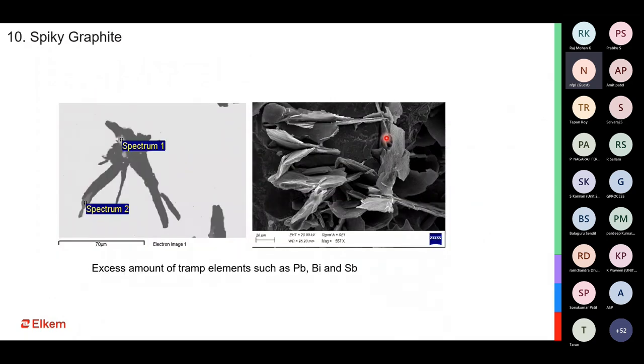Spiky graphite. Again, spiky graphite is something which can happen in both gray and ductile iron. In gray, it is kind of Widmanstatten, but in ductile, these spiky graphites happen when you have a lot of anti-nodulizers like bismuth, antimony, and lead. When they are present in excess, they can cause the graphite structure to be not a sphere, but more like having spikes. And that is the spiky graphite that we see in our castings. That is something which can only be controlled by having control on these tramp trace elements in our system.